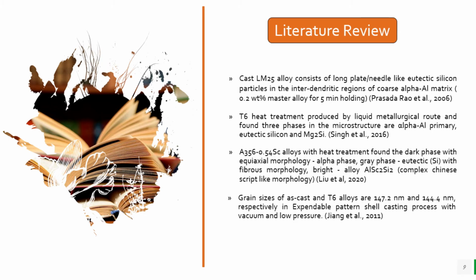Next, from Singh et al., they got a T6 heat treatment produced by liquid metallurgical route and found three phases in the microstructure. The three phases of the microstructure are alpha aluminum primary, eutectic silicon, and magnesium silicide (Mg2Si).